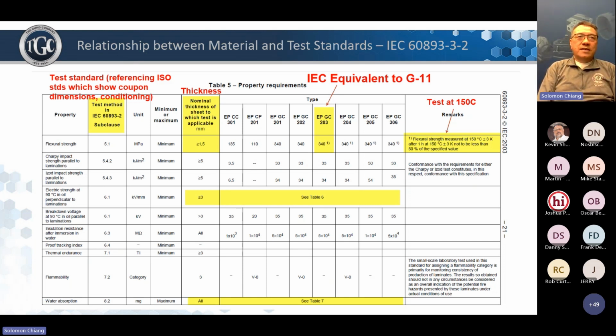and then you look across for thickness. It says greater than 1.5, greater than 5 millimeter, but then you say, hey, some properties are thickness dependent. Okay, IEC would ask you to go to a different table to look at properties that are thickness dependent. And then for elevated temperature material, like the 4 on the right-hand column, that's superscript 1. That means you have to read the remarks. The remark tells you that for elevated temperature, it's supposed to be half of the specified value at room temperature.